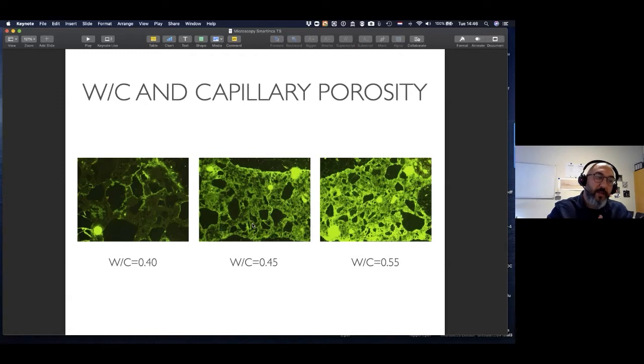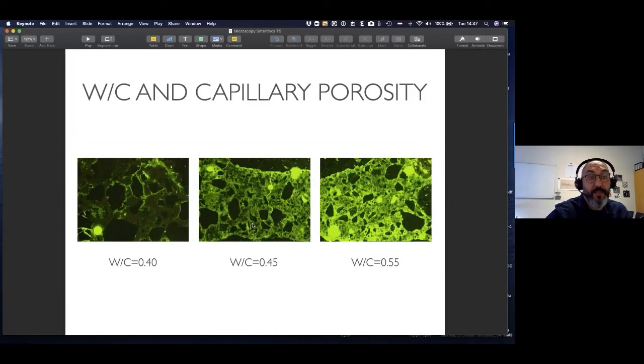That's the reason you see darker microstructure. And as you increase the water-cement ratio, you increase the amount of capillary pores, and you can observe that again under the microscope. And please note that when we took these images, all the light conditions were the same. So we did not change the light intensity on our microscope. You keep the microscope light conditions the same, but when you observe these different water-cement ratio microstructures, you will of course see different intensities. And if you correlate them, you will see that there is a very linear relationship between water-cement ratio and the amount of capillary pores.